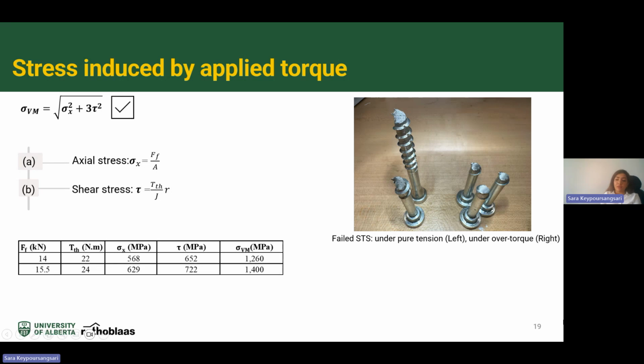In the case we over-torque the screws, we have axial stress and shear stress. Therefore, we use the von Mises stress to find the stress on self-tapping screws, and you can see how shear stress affects the results. In the failed screws in group B, we calculated the von Mises stress, and we found that in these two cases it was more than the yield strength, and that's why we got the failure in these screws.